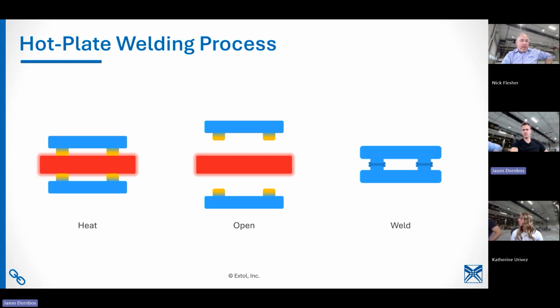So hot plate, and it also depends on, and this is true for all plastic welding, if you have glass, talc, regrind, which I'm assuming everyone on the call has dabbled in some of those sort of fillers, it can affect your strength. We typically see it negatively, especially with hot plate welding, because those glass fibers don't really cross the barrier of the weld joint. So typically it's a reduction.